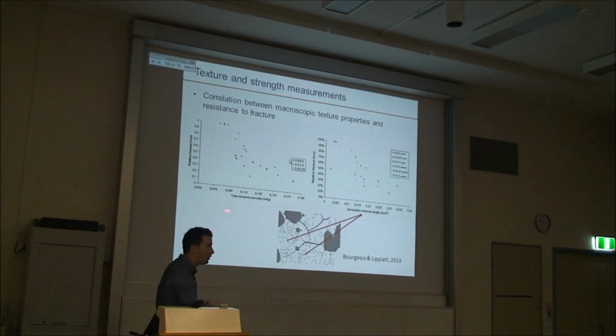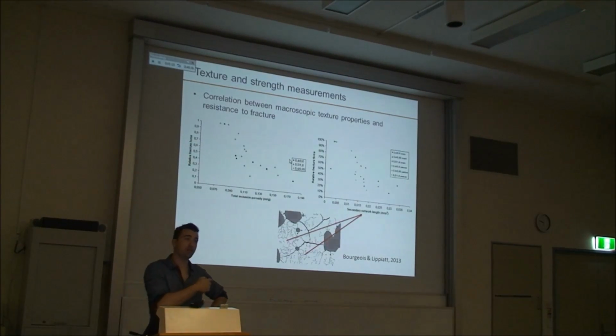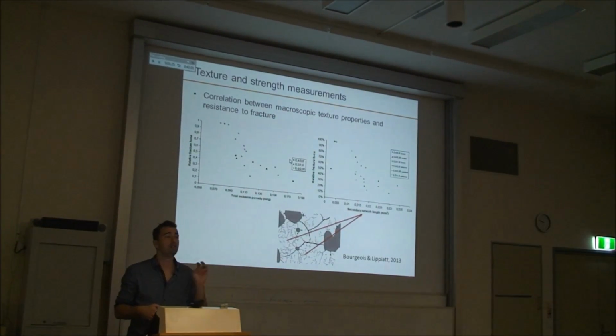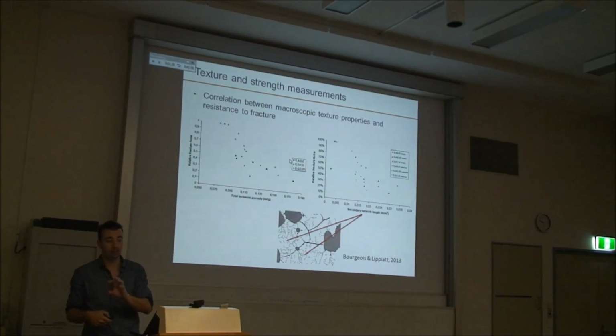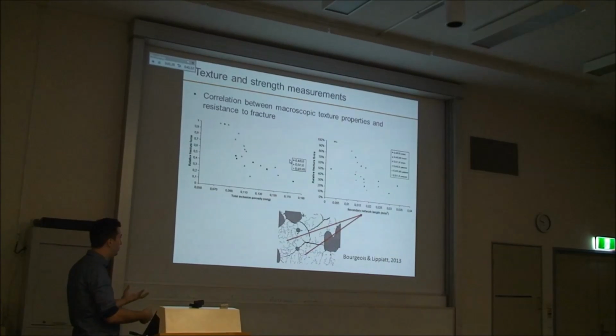So this is a reduction in fracture force related to the total inclusion porosity. So the porosity is actually a macroscopic texture property. Here they've correlated the porosity with the fracture force. So this is already showing that there are textural properties that drive the mechanical breakage. The other graph here on the right is the same fracture force, so the reduction in the force necessary to break the particle. And you see a reduction in the fracture force with the length of the secondary fracture network. They measured the length of those little cracks here, how much crack there is per surface area.